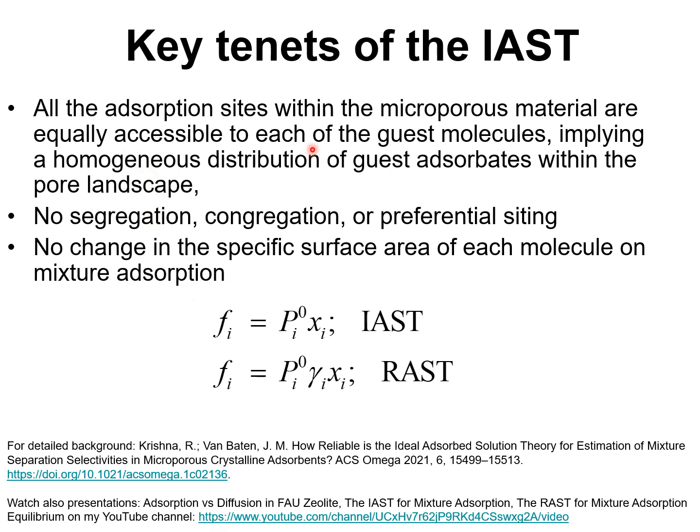All the adsorption sites within the microporous crystalline material are equally accessible to each of the guest molecules, implying a homogeneous distribution of guest adsorbates within the pore landscape. No segregation, congregation, or preferential siting of any of the guest species in the mixture.